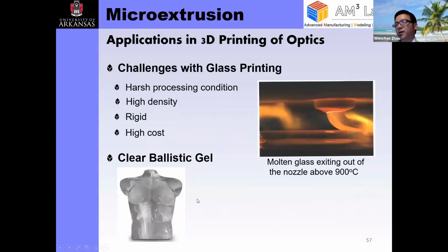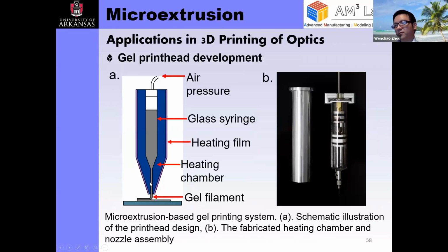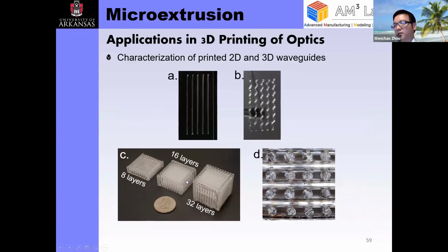And we also expanded this micro extrusion printer into printing some optical materials. One of the things of printing optics is that it's very difficult to print glass because glass requires very high temperature to operate. So we looked at a material, the clear ballistic gel, and we noticed this material to be very promising. So we developed a printer head to print this material with some heated chambers, and because it melts at only 100 C, it's much more manageable. And we were able to print some patterns of these layers with this clear ballistic gel.